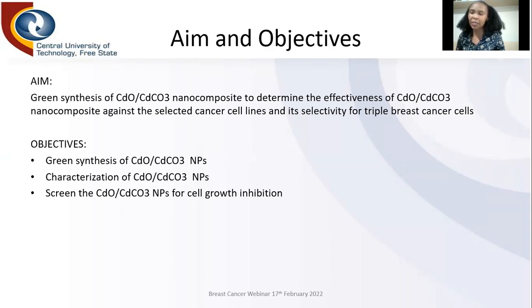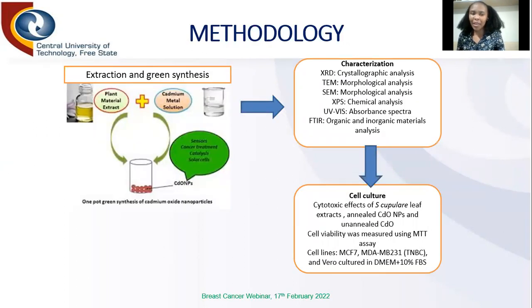The objectives that will be met by this study, or rather that have been met by this study, include synthesizing the nanoparticles using the green synthesis technique, characterizing them, and screening the nanoparticles for cell growth inhibition. Okay, the methods that were utilized, of course, it's the green synthesis, but prior to green synthesis, extraction is mandatory. In this study, water was used as a solvent, and the plant material used is Synadenium cupulare leaves, which were found in Limpopo in South Africa. And the reason Synadenium cupulare was used is because historically it was used as an anti-cancer remedy or anti-cancer agent.